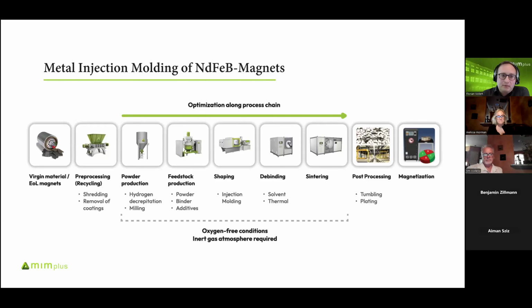So what we do, we start with our virgin material or our end-of-life magnets. For the end-of-life magnets, we have a pre-processing step, which includes, for example, the removal of the coatings. With the virgin material, we can skip that step and go directly to powder production. The powder is then used to produce a feedstock that is flowable and can be used for the shaping in the injection molding machine.